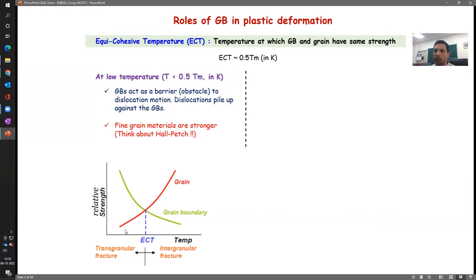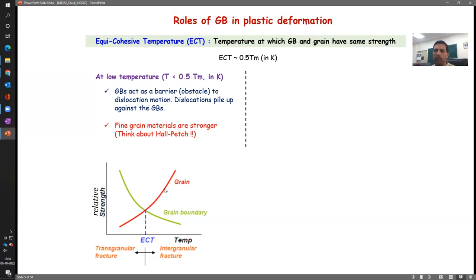There must be a temperature where the strengths cross, and that temperature is called the equicohesive temperature. When testing below the equicohesive temperature and if it fails by fracture, it will usually be transgranular fracture because grains are the weaker region. If it is happening at a temperature higher than the equicohesive temperature, grain boundaries are relatively weaker, so fracture would occur along the grain boundaries — that is intergranular fracture.